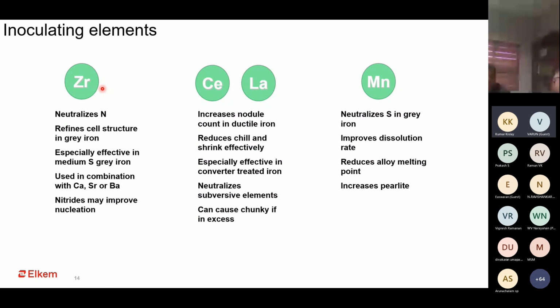In combination with strontium, zirconium inoculant also helps in controlling the length of graphite flakes in grey iron, and also the coarsening of graphite flakes. So for foundries having type C graphite problems, apart from definitely controlling the carbon equivalent, a zirconium strontium inoculant helps. Also for foundries producing grey iron castings with both heavy and thin sections, a plain strontium inoculant may or may not be useful. There, a combination of zirconium and strontium does give a very good effect.